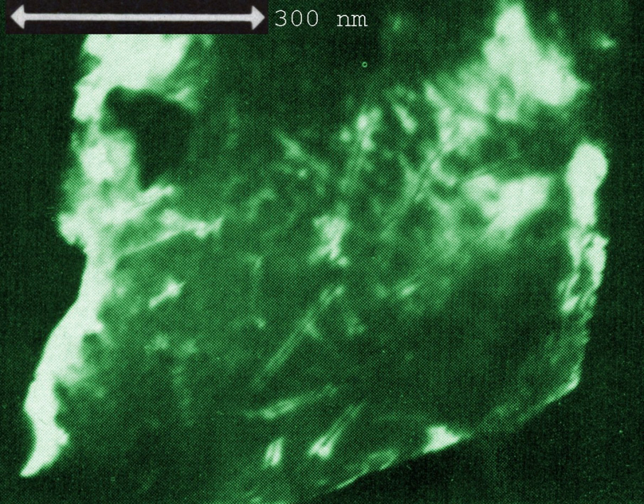According to the ion explosion spike model, the primary ionization induces an atomic collision cascade, resulting in a disordered zone around the ion trajectory. According to the electron collision cascade model, the secondary electrons induce a radiation effect in the material, similar to a spatially confined electron irradiation. The electron collision cascade model is particularly suited for polymers.